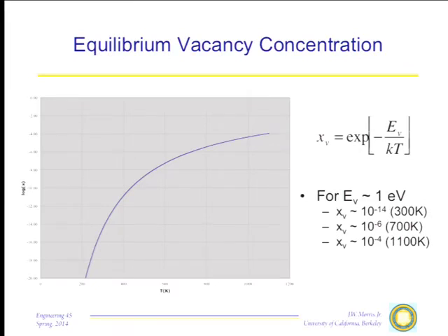That has a big consequence. Because as we discussed way back when we talked about vacancies, one of the main things these vacancies do is that they allow atoms to move through the solid by exchanging with the vacancies. Well, if I've only got one vacant site in every 10 to the 14th, I'm not going to see much motion because the atoms aren't going to be able to find vacancies to exchange with. The net result is, and we'll see this again later, down around room temperature, solid state diffusion of substitutional species is just about dead zero. It just doesn't happen.